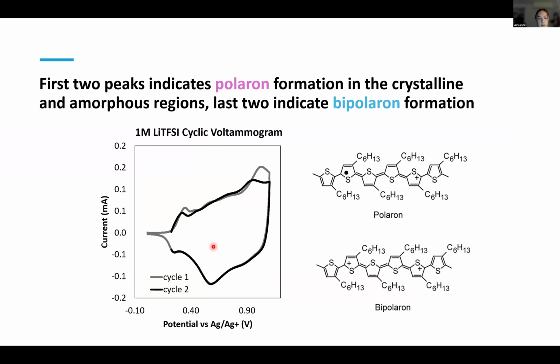And we know from previous studies that these first 2 peaks correspond to polaron formation in the crystalline and amorphous regions of the polymer, respectively. And we're not super certain what's happening on these last 2 peaks. So we're particularly interested in what's happening at these high potentials, and especially how it changes depending on the anion.